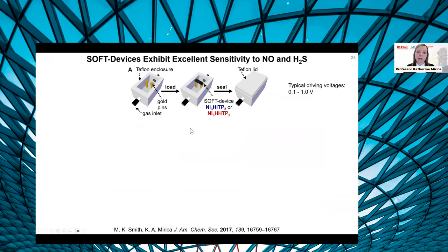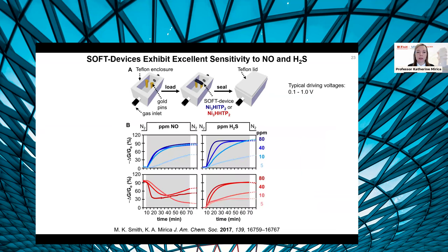To probe the sensing function of these textile devices, we can place them into a custom-made enclosure and flow gases over their surface and observe the response. So in this case, we're exposing two different framework materials. The one in blue is a nickel-based framework interconnected with nitrogen-based heteroatomic crosslinkers, all relying on the hexaiminotriphenylene ligand that I've shown before. And the one in red is interconnected with oxygens, so metal bis-dioxolene types of linkages.